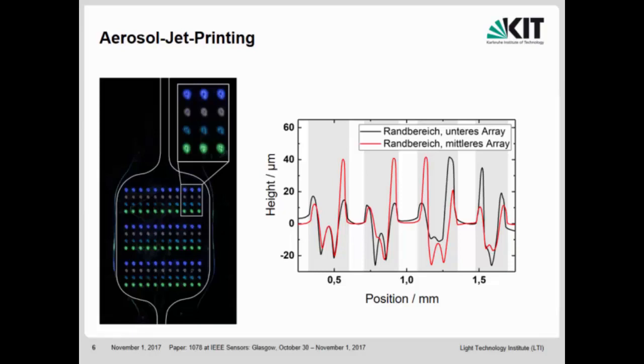So the problem was simply that there was a little bit too much solvent within the ink when it hits the substrate, which dissolves this, and then you have something like a coffee staining effect, which you probably know. If you take a drop of coffee, put it on your desk, and it dries, then you have this dark ring on the outside, and this is due to the different drying and the different concentration of the material within the solvent, and then you have these Marangoni flows that cause the diffusion to the edge. And this is what happens here, and unfortunately, additionally, we dissolved the material from out there. So what we ended up having here is not the pure material, it seems to be a mixture of the polystyrene and the fluorescent dyes.